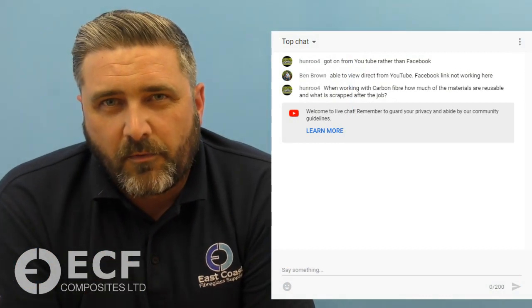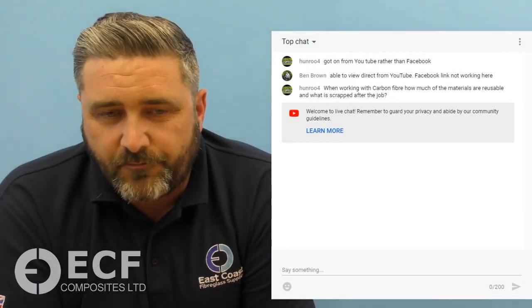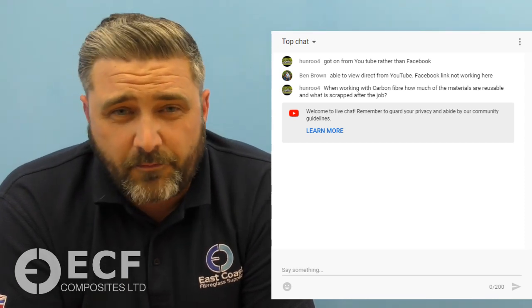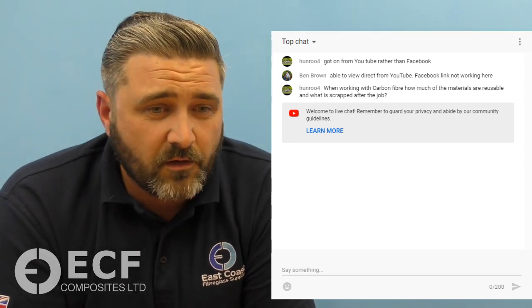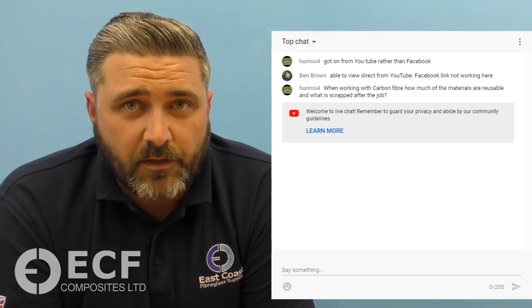If it's a PVC door, you'll probably not get a great bond to it. Fiberglass will naturally release from PVC. Anyone who uses the material will know that if you use PVC buckets, the resin will just easily bash out of the bucket to reuse the bucket again. You can use Microseal T20 as a promoter to help it adhere to the PVC. Do your patch. It's a pretty good idea just to spray it over, disguise it. Composite doors, they're polyester based, I believe, so something like a composite door should be able to be repaired with the material.